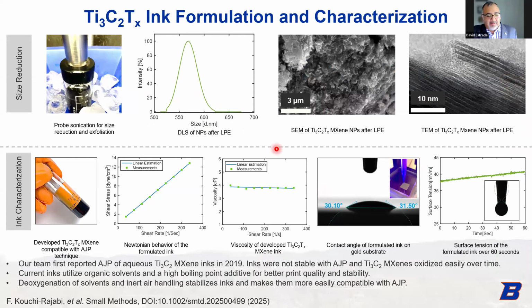So we've been targeting aerosol jet printing for now with the MXenes. And for aerosol jet printing, the particle size has to be about 200 to 500 nanometers in lateral dimension, right? Larger than that, you risk clogging your nozzle. Titanium does oxidize fairly easily, especially when you reduce particle size. The Ti3C2 oxidizes quite easily. Some of the other MXenes, like niobium, really oxidize quite a bit.